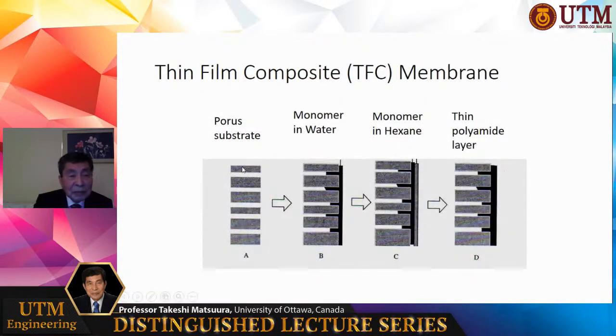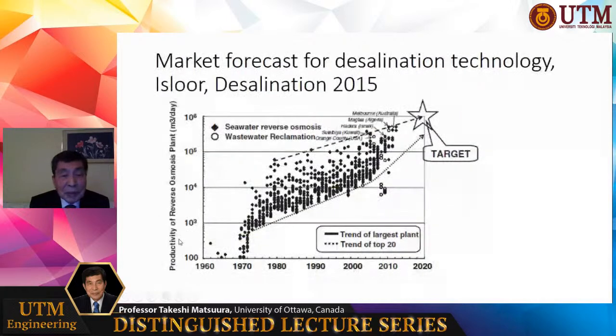Porous substrate, this porous material, is put into water, which means the solution of monomer A, and then it is put into hexane, which means solution of monomer B, and at the interface, polymerization takes place and a thin polyamide layer is formed. It is called thin film composite membrane because this layer is very, very thin. From now, I often use thin polyamide layer. It means this thin layer of polyamide with tiny, tiny pores. Now, this is how to make the membrane.